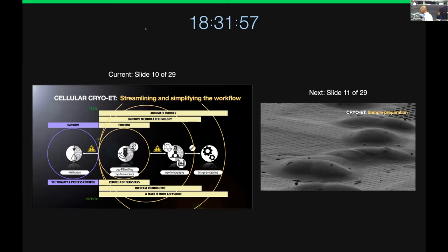And second, the FIB milling itself, since we are now using both gallium and plasma. For normal cellular samples, we are in a range of 20 to 30 minutes per lamella. For the plasma FIB for tissue, I think we are in the same range, but for the tissue samples where you have to do the trench milling, depending on what kind of ion you are using, you are slower or faster. And that would be a question Bob Glaser normally asks: how much damage do you cause when you do this type of milling? How far do your ions penetrate your samples, and also the molecules you would like to investigate in the end?